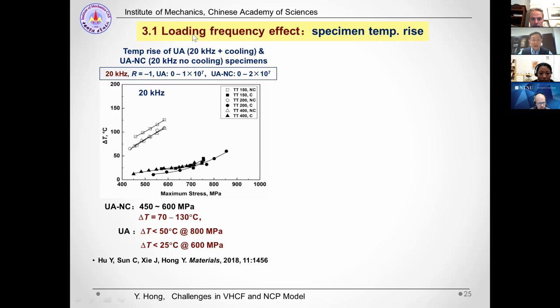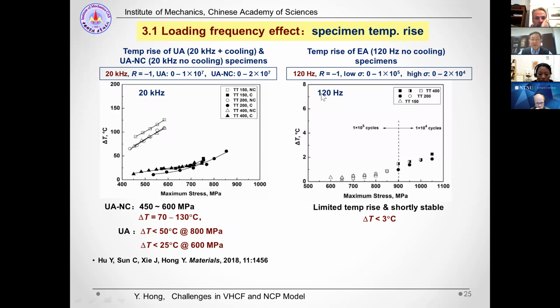We have this type of result to show. For the specimen without cooling under ultrasonic frequency loading, the temperature rise is between 70 and 130 degrees. But if the specimen is subjected to air cooling, the temperature rise is somewhat smaller. For the case of very high cycle fatigue testing, the temperature rise is less than 25 degrees. But for the loading frequency of 120 hertz, which is a kind of conventional frequency, the temperature rise is very limited, less than 3 degrees.